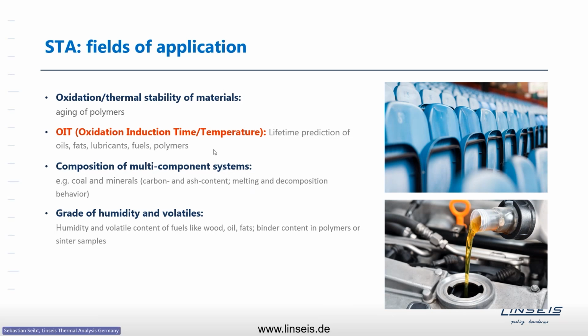And there's the DSC experiment, the so-called oxidation induction time. In that case, you measure the heat flow signal, you start in an inert atmosphere, bring the sample to a certain temperature, then you switch to oxygen, and then you measure the time, how fast you get a response signal showing you the heat flow change of the beginning oxidation. And the oxidation induction time in combination with the mass change of a sample in oxygen atmosphere gives you a pretty good prediction of lifetime, prediction of aging, and that's frequently used for polymers, for oils, organics in general, fats, and whatever.